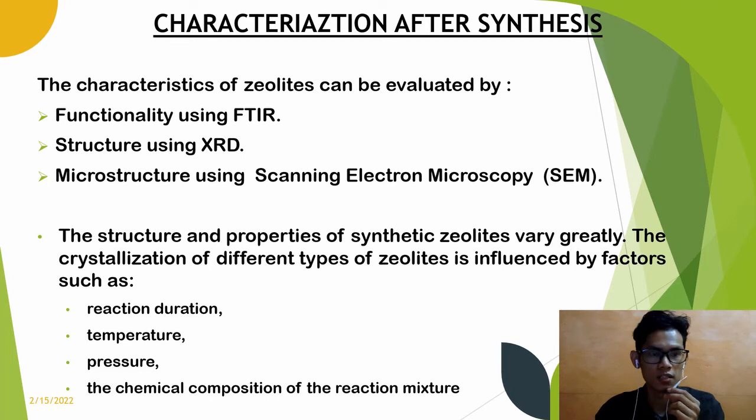The characterization of the zeolite can be evaluated by using FTIR for the functionality, using XRD for the structure, and scanning using SEM for the microstructure. The structure and the properties of the synthetic zeolite vary greatly. The crystallization of different types of zeolites is affected by factors such as reaction duration, temperature, pressure, and the chemical composition of the reaction mixture.